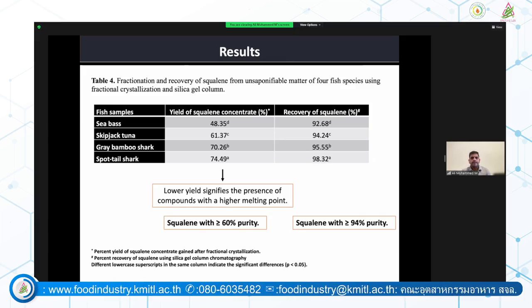After fractionation, we found different proportions of squalene in the different fish we extracted, which are commercially available in some regions. And we can see that after fractionation, the purity of squalene was almost 60% with just 2 steps of process: extraction and fractionation at -20.